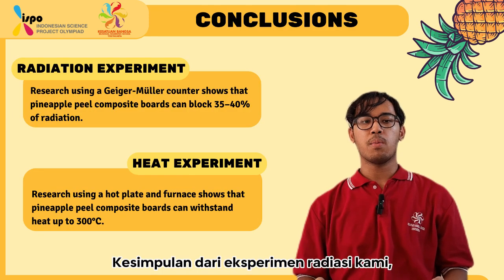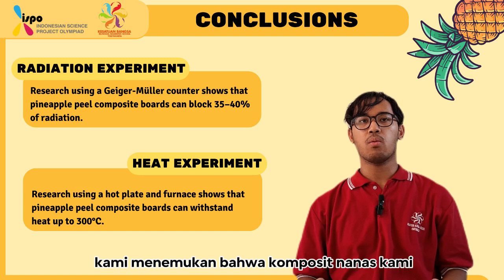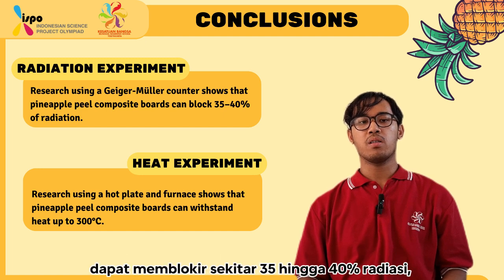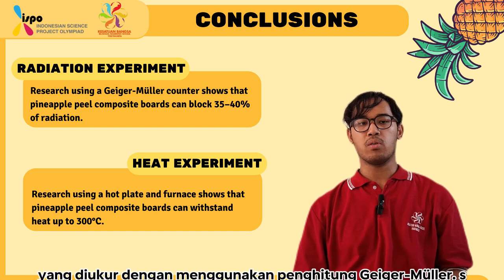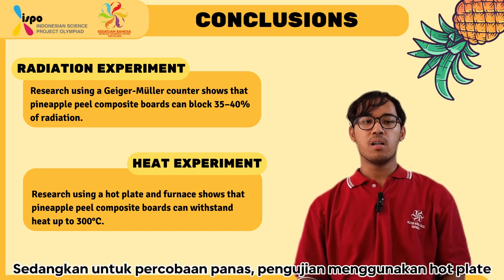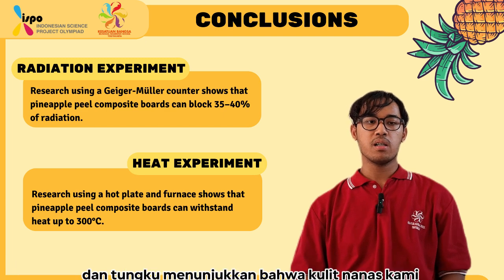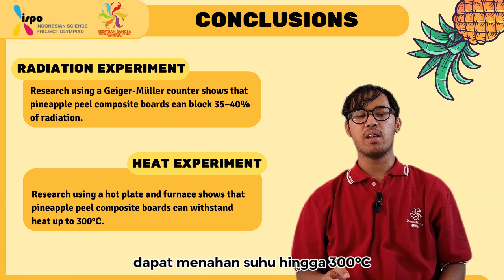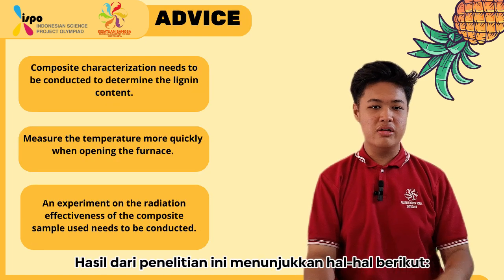In conclusion, from our radiation experiment, we found that our pineapple composite can block around 35 to 40% of the radiation as measured using a Geiger-Müller counter. As for the heat experiment, the tests using a hot plate and a furnace showed that pineapple peels can withstand temperatures up to 300 Celsius. The result of this study suggests the following.